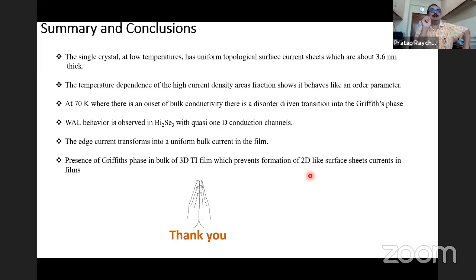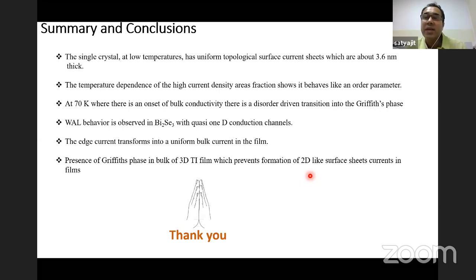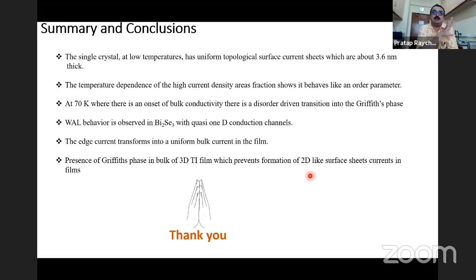And one final question about this thin film data on bismuth selenide. Yes. In a thin film, I don't know this very well, but what I read is that you have the top and the bottom surface. Below 5 nanometers, you actually cause a hybridization of the surface and it ends up as a trivial insulator. Yes, that is not the case here. This is 30 nanometers. I see. Okay. Thank you.